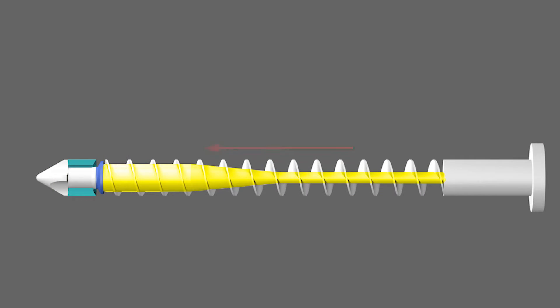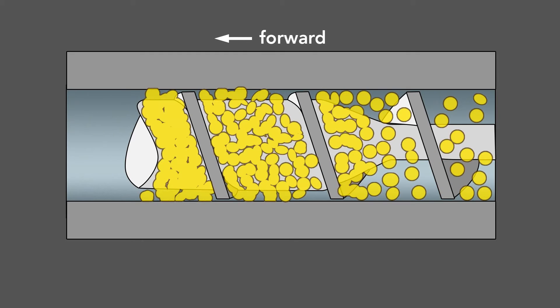And third, the screw action itself heats the plastic throughout. The shaft's diameter increases along the screw so that the distance between the wall and shaft decreases. The flights then squeeze out air as they move the plastic forward, and they shear the pellets and press them against the barrel's wall. This shearing creates friction and heats the plastic throughout. This screw-induced shear supplies a majority of the heat needed to melt the plastic — between 60 and 90 percent — with the rest from the heater bands.